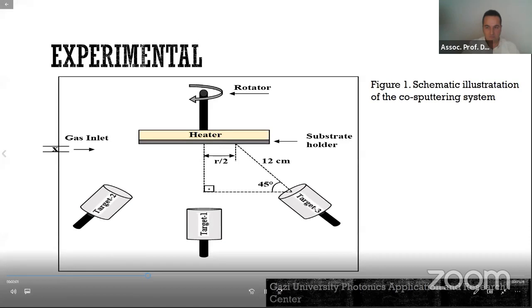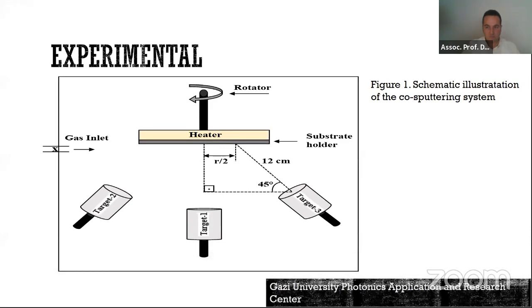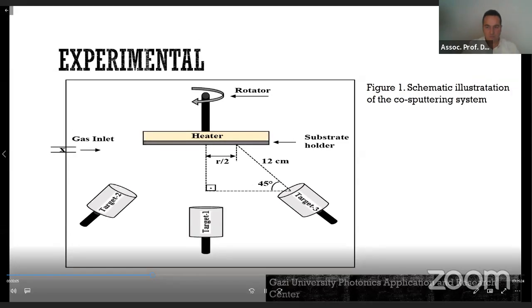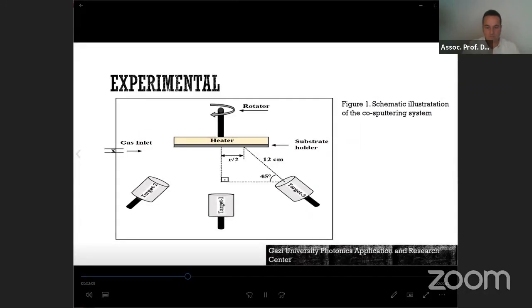A target that is desired to be deposited is bombarded with energetic ions of inert argon gas. We use argon gas in this process. The forceful collision of these energetic ions with the target ejects target indium and sulfur atoms into the space. These indium and sulfur atoms are then deposited on the substrate material, forming an indium sulfide thin film.